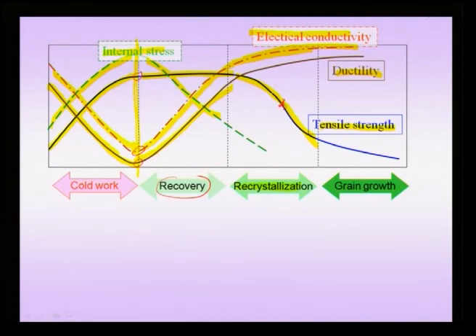So I have this arrow along which it goes, and therefore now my recrystallized material is weak, that means my tensile strength decreases. Of course, it does not fall down to the lowest value possible, and this actually tends to happen only during grain growth. During grain growth there is a further decrease in the tensile strength, and therefore my material tends to lose its strength. My ductility already has come to its original near maximum value. You get a little more benefit, but not much. Sometimes ductility may even come down because of the increase in grain size, but here we note that the important change is to the tensile strength, which continues to fall if my grain size increases. This is due to the Hall-Petch effect.